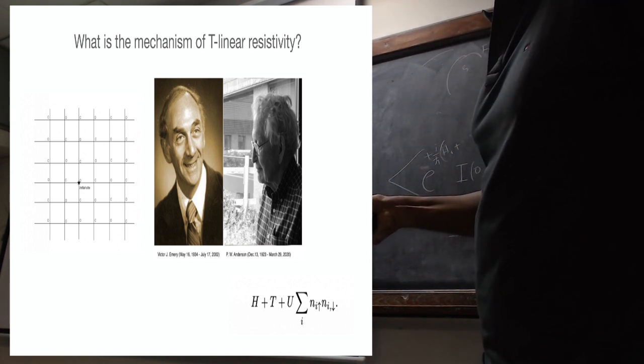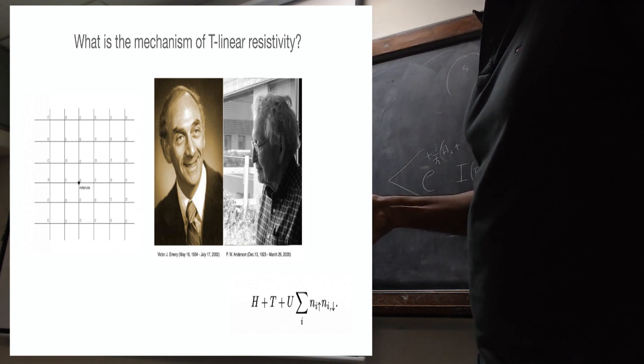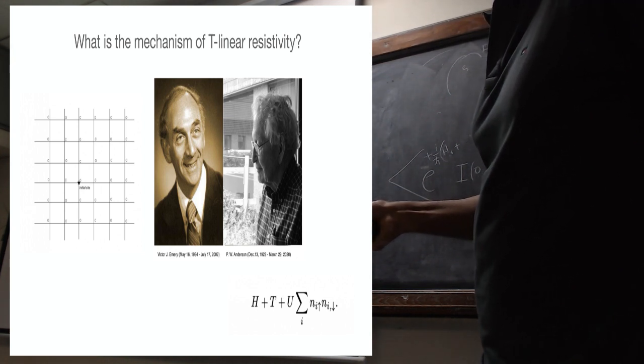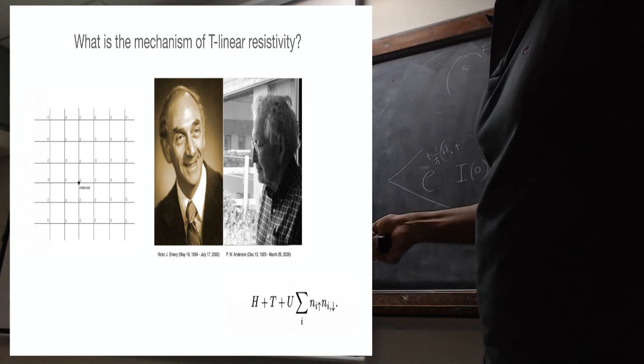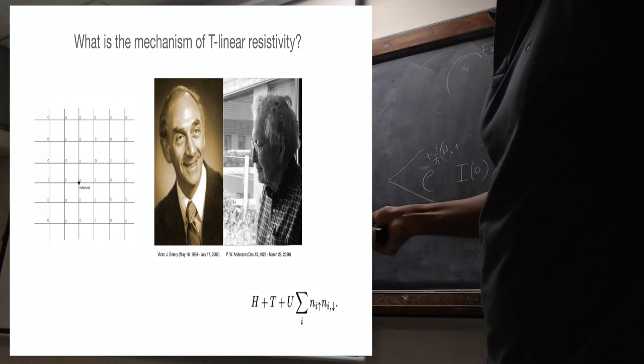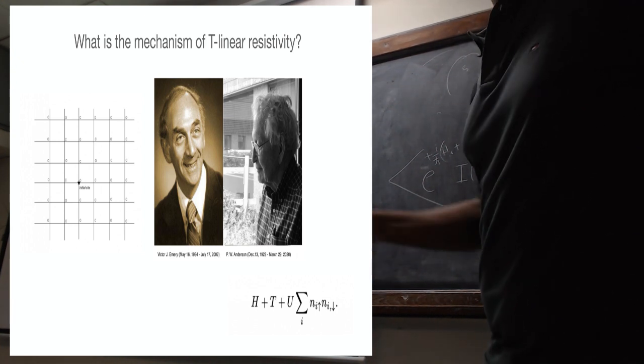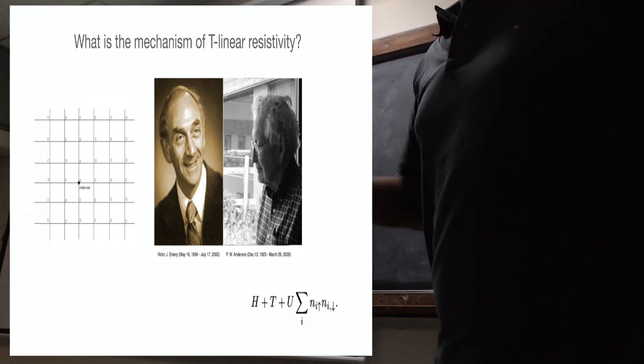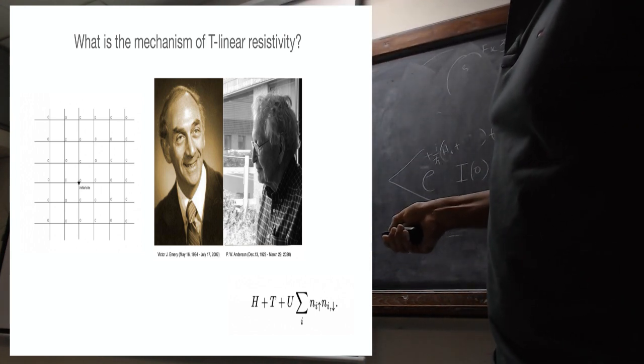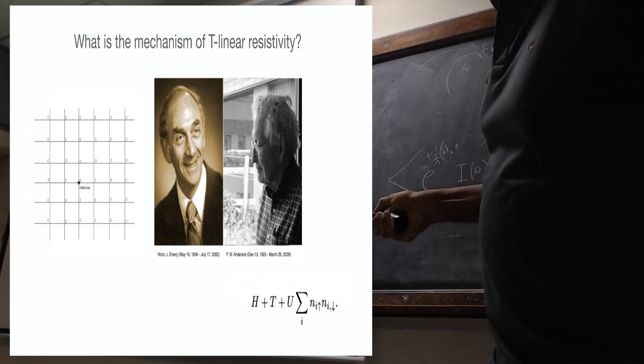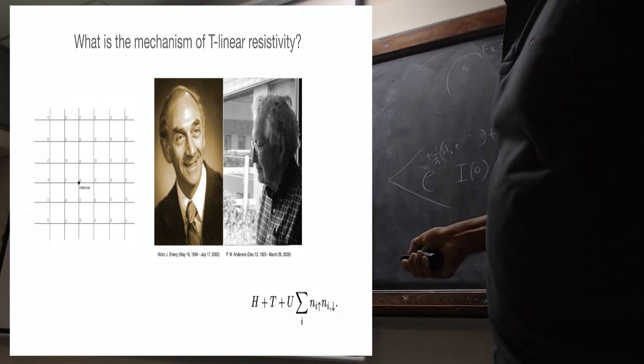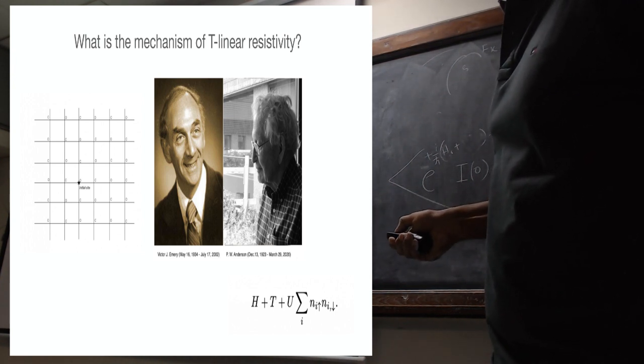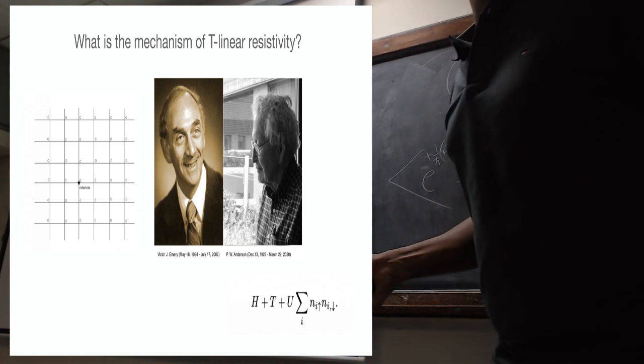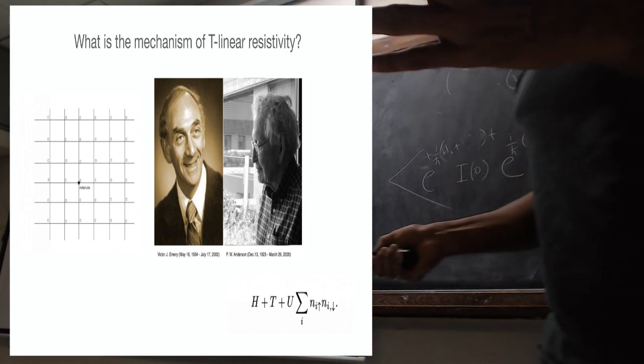Anderson said that you look at copper spins. So this is the kinetic energy, this should be an equal sign, the kinetic energy of the particles on copper, and then there is a strong Hubbard repulsion on copper when you put two electrons on one copper site. It's called Hubbard U. It's a simple model. But Emery argued that this simplicity is good, but you are oversimplifying the problem. You are actually throwing the baby out with the bathwater.